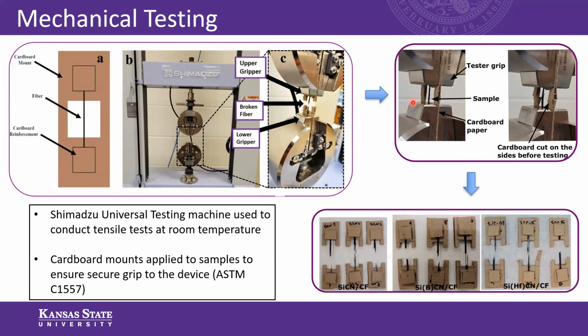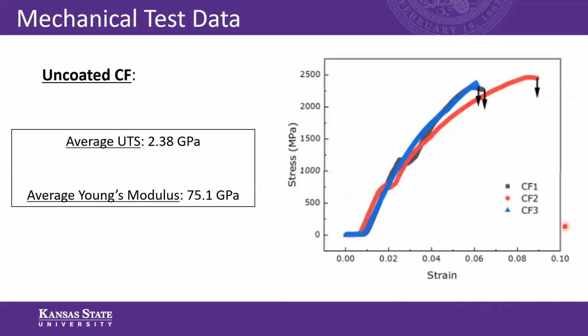So this is a more close-up image, which shows the cardboard mounts being secured onto the tensile grips. And then, of course, before testing, these two ends were cut off to ensure that all of the loading was properly placed on the sample itself. And this is an after image of all of the samples. For mechanical testing data, we also went ahead and tested some uncoated carbon fiber for the purpose of comparison. And as you can see, the results were quite consistent. The uncoated carbon fibers reached an average ultimate tensile strength of 2.38 gigapascals and an average Young's modulus of 75.1 gigapascals.